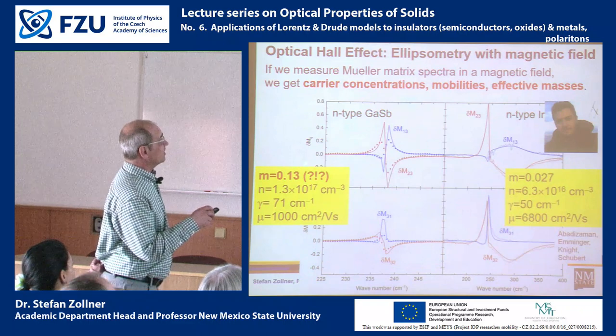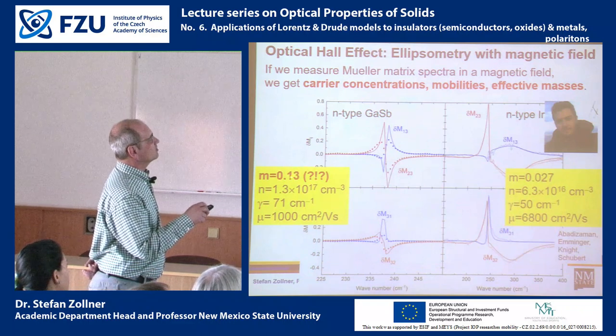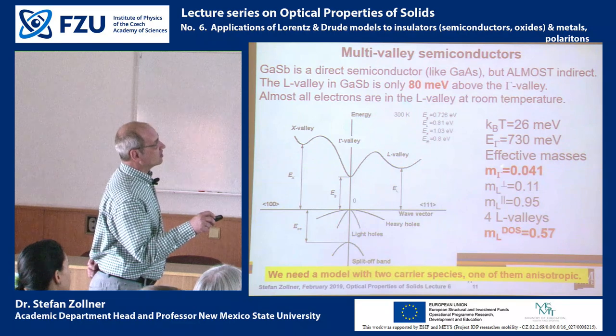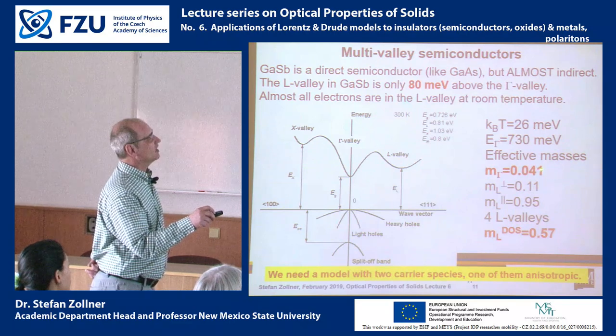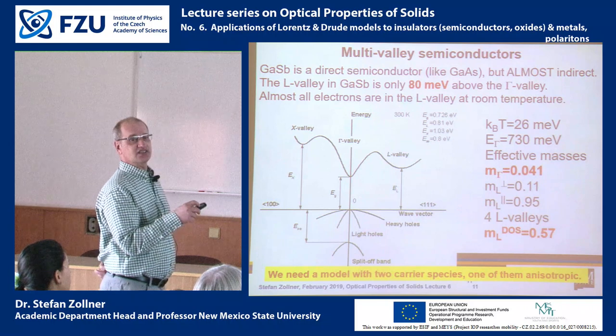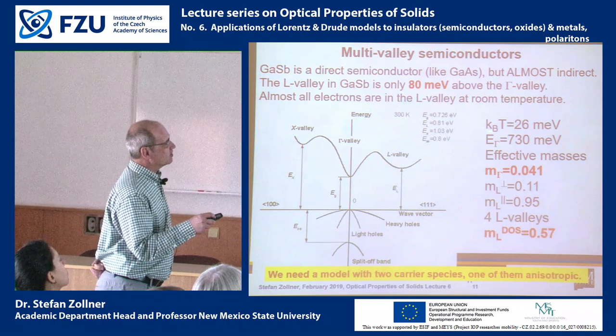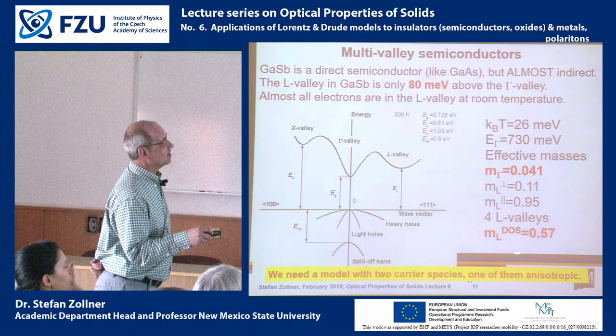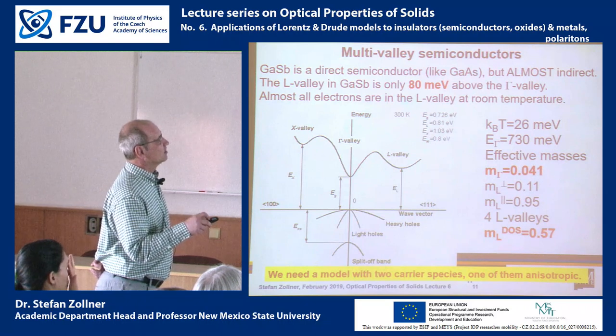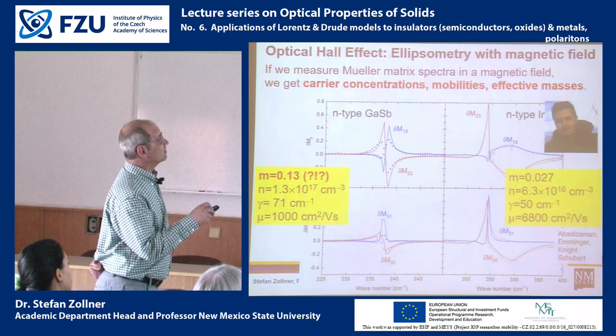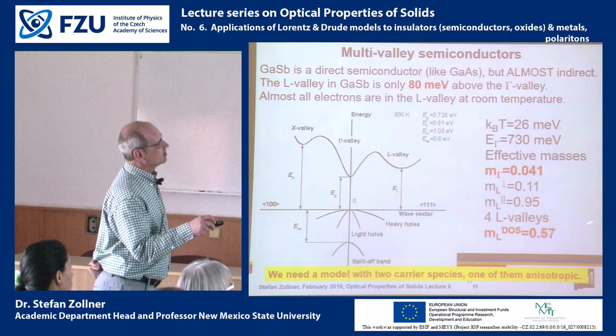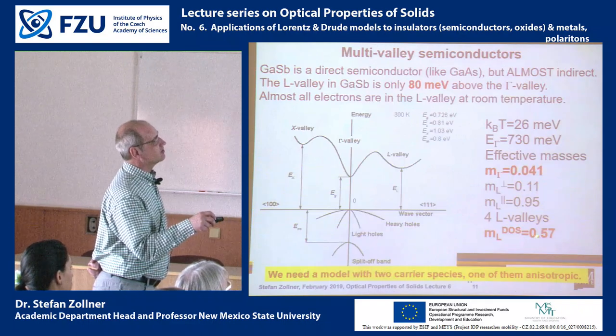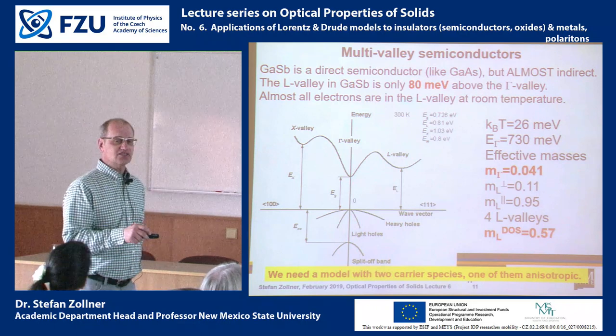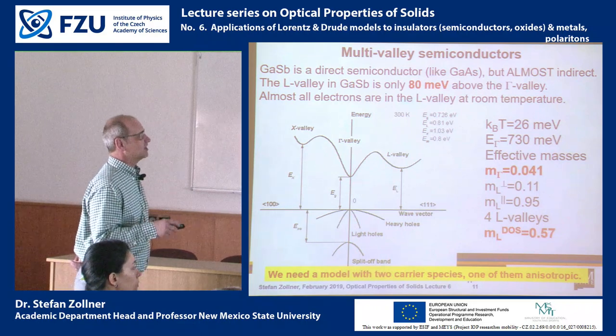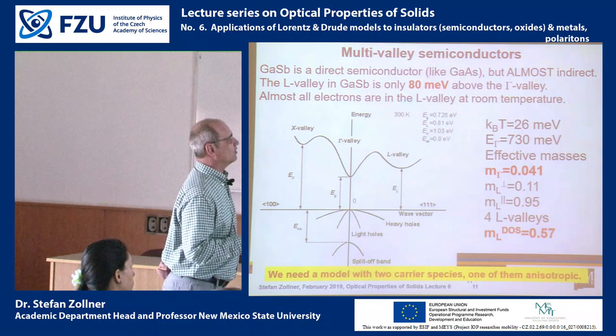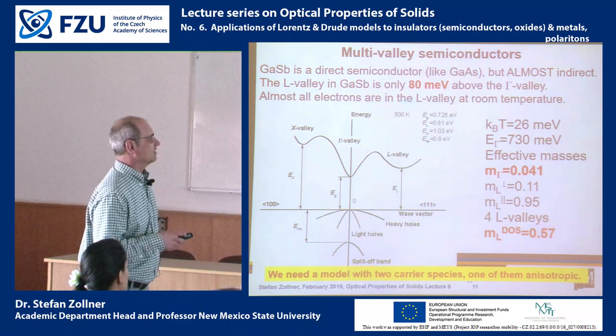So we measured an effective mass of 0.13, which is much larger than the 0.041. However, the reason we're getting an effective mass which is larger than the gamma valley mass is because some electrons will be in the L valley. So the 0.13 mass that we had for gallium antimonide is actually some sort of an average of these two masses. And we're doing calculations to figure out how we can quantify that.